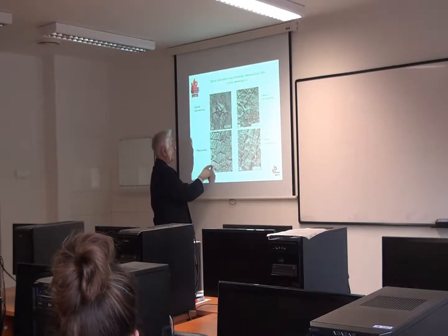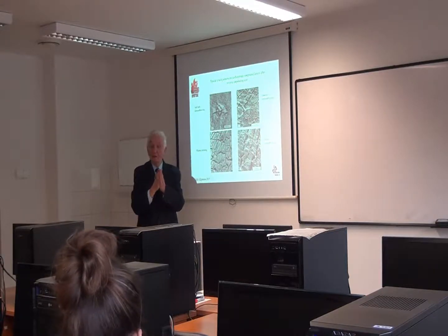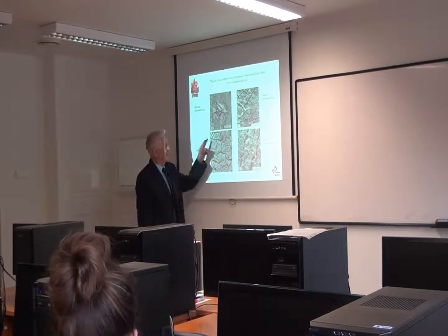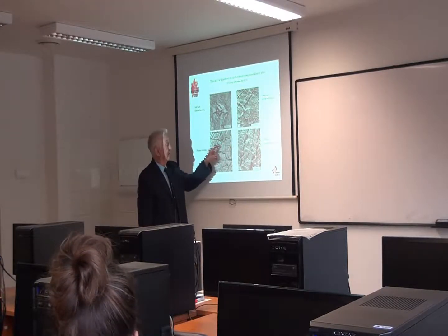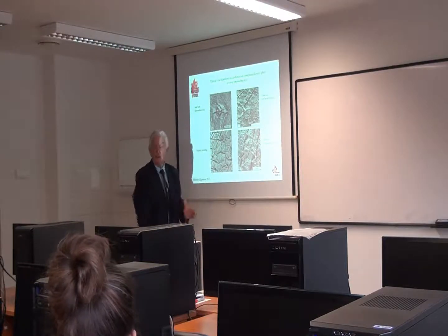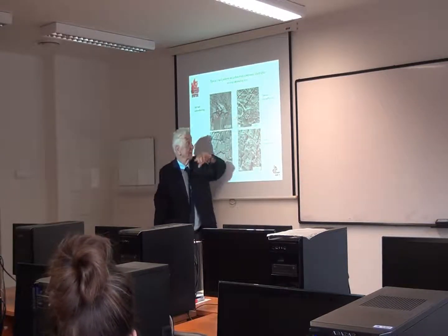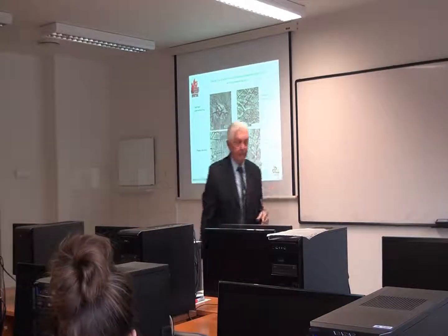When you take plasma nitriding, for instance, it's very interesting. It doesn't form the network of cracks at once. First, it will form a network of parallel cracks, and then sliding. So it's a very complicated, very sophisticated part. This is for plasma nitrocarburizing, and this is for gas nitrocarburizing. You see, it's a random kind.